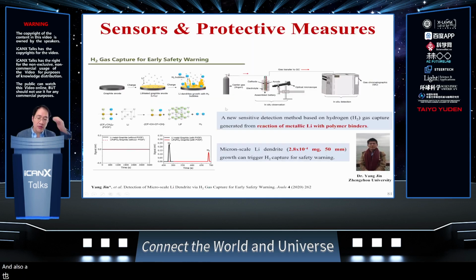And also, you can do a lot in terms of sensors. And this is not my work. This is done by my ex-student Jin Yang in Professor Yi Cui's group. He's looking at this issue of the graphite anode. We know that at fast charging, it can precipitate out lithium metal. And that can induce local shorting, which is very tough to handle and very difficult to detect. But his insight was that when that happens, you actually generate some hydrogen gas. And hydrogen is actually very difficult to seal in. And that generally is a very difficult problem for the hydrogen economy.